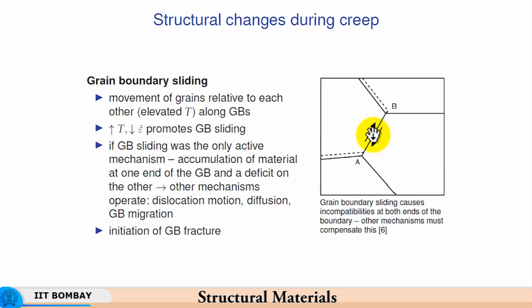So, that is the reason why the process is diffusion controlled. For example, if this is grain boundary sliding that is taking place, and then it introduces deficiency of material on one side and excess material on the other side, we need some transport mechanisms to maintain the continuity of the material, to prevent any discontinuities in the material from being created, and therefore, we need mechanisms like diffusion and grain boundary migration to take place, so that these deficiencies get compensated for, material which was in excess here gets transported here.